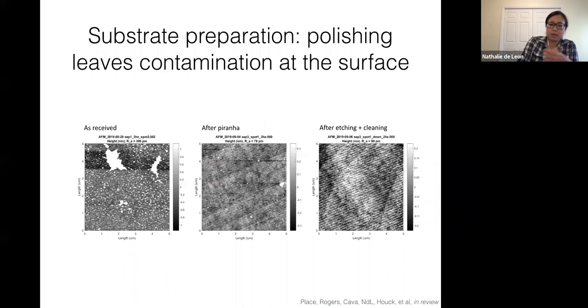The first thing that we did was look at what was going on with the substrate. In fact, the as-received sapphire substrates that we get from the company have quite a bit of contamination at the surface. Even just looking at AFM, you can see that there's a lot of little dots everywhere, and they generally don't get removed with conventional solvent cleaning. So we applied a lot of aggressive acid cleaning and also some very gentle wet etches of the sapphire surface, and we can now get these very smooth and clean sapphire substrates.